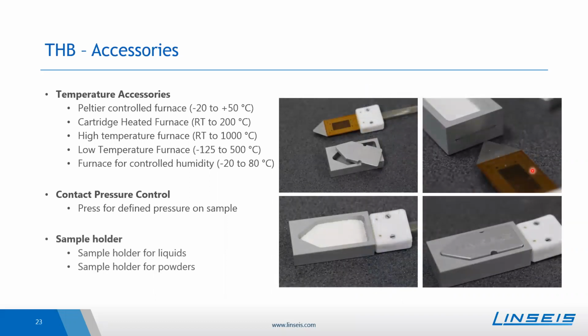For solids, you have this manual press, more or less as a sample holder, but for liquids and powders, we also offer a sample holder. Here you can see pictures of our powder sample holder. It is a container where you fill in your material, bring in the sensor from the side, and then fill it up with the powder. Then you can close it and also realize pressure-dependent measurements. For liquids, there's also a special sample holder available to easily realize this kind of application.